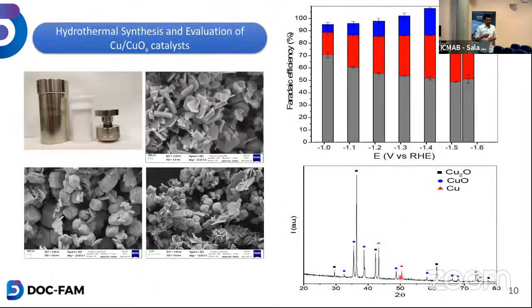And then I had to choose the next step because the small nanoparticles are not so good for my type of electrode reduction. So then we found some articles that are quite promising, published in top journals. Not only the small nanoparticles or very big size of the particles can help, but the optimum range of the nanoparticles can actually help in the reduction mechanism. So what I've done is directly I have taken a copper precursor and carried out the synthesis in a conventional hydrothermal reactor with an autoclave.